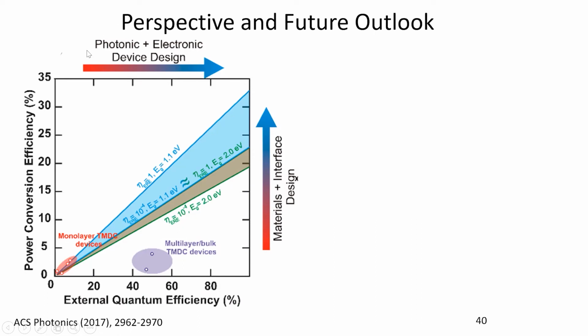My sense is that in the coming years, these two will be taken care of very well. In fact, I can tell you there are unpublished reports where people have been seeing very high external quantum efficiency. So this is not that hard to take care of. The harder thing to take care of is materials and interface control. And this is where, even if you are able to get very high external quantum efficiency devices, the power conversion efficiencies are going to stay low unless we work hard on, say, the open circuit voltage.